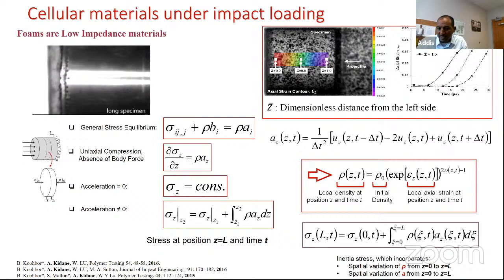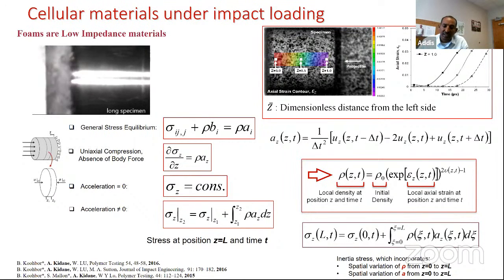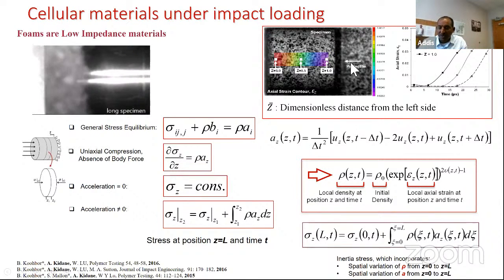The reason is that it's not as simple as we think to understand these material behaviors. From an experimental perspective, these cellular materials are low impedance materials. That means the material response under impact loading depends on the propagation of stresses. If you see the video running here, you impact this side, there is a large deformation on the left side, whereas the right side doesn't see anything until the stress wave reaches that side. On the right side, where you have the digital image correlation images shown here, there is a time delay between each position where the strain reaches that position. So the traditional way of measuring this response by having a load cell on the backside or other methods doesn't work because the material response is not uniform in this case.